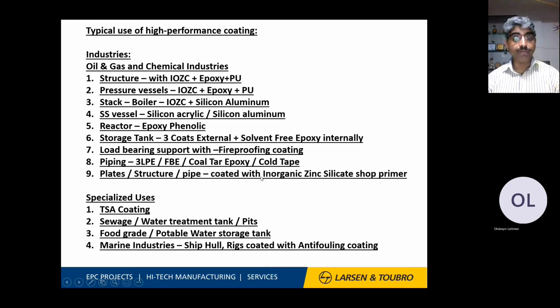Other plate structure, pipe, coating with inorganic zinc silicate shop primer. This is nothing but a transit primer by which you can ship such pieces to different areas and then do the final coating at the end, where you want to do a lot of dress-ups and welding at site.